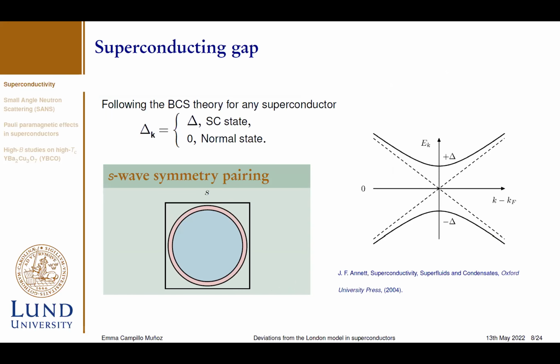So an important feature of superconductivity is that when we are in the superconducting state, the material develops a gap around its Fermi surface. This is well explained by the BCS theory. Following this BCS theory, our order parameter will be given by this superconducting gap. When the material is in its superconducting state, we will have this gap around the Fermi surface. However, when the material comes back to the normal state, it will be zero, and then it will behave as a normal metal.